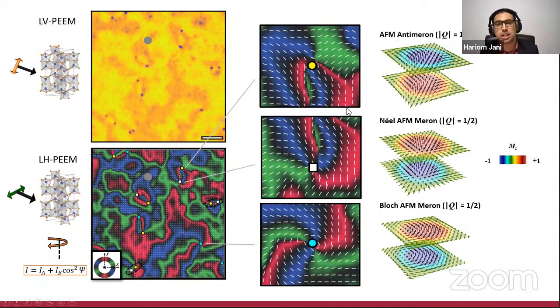Likewise, we have an object which is the Néel AFM meron, which is some kind of outward pointing structure. And then we also have the anti-meron, which consists of the opposite winding in comparison to these two objects, which is very clearly shown here, given the diverging kind of structure. So we can very straightforwardly identify the topological charge half entities in the system. Once again, as you notice, I've only given the modulus value of the topological charge, not the absolute value, because we are not able to distinguish the core orientations, and therefore we only know this to a certain modulus value.